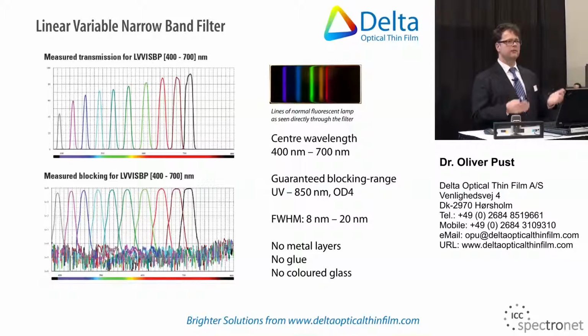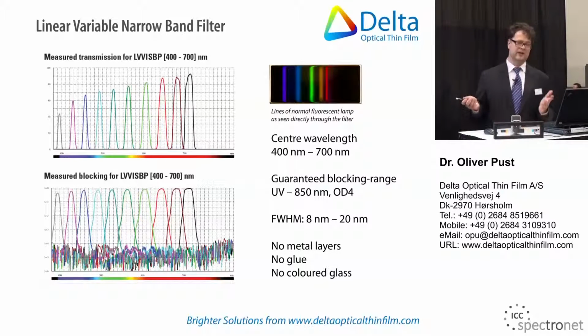Now let's go away from the edge filters to the bandpass filters. That was our first bandpass filter. It's a filter for the visible range from 400 to 700, with broadband blocking exceeding the tuning range of at least OD4, and a bandwidth that is slightly higher than 2.something% of the center wavelength. And again, no metal layers, no glue, no color glass, which makes this filter also applicable for laser applications.